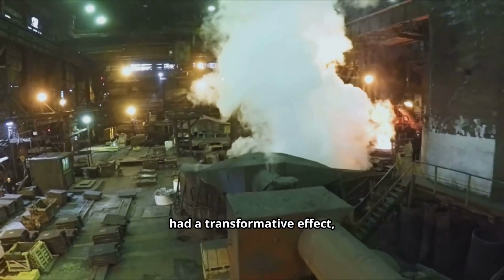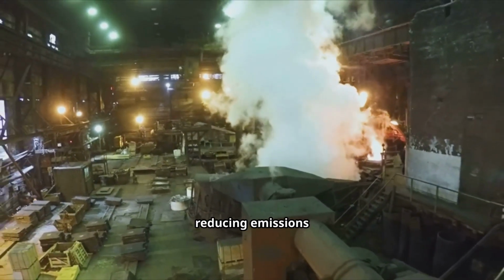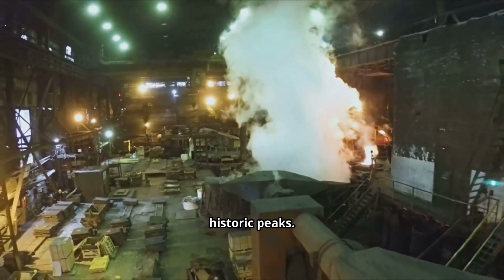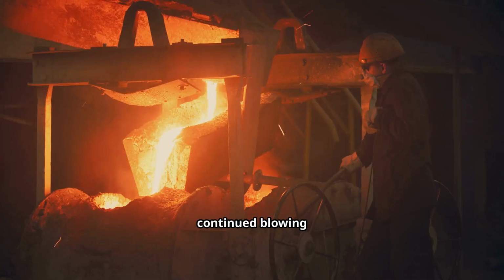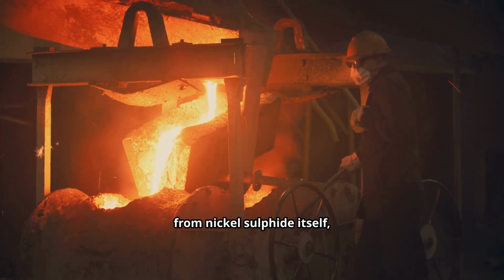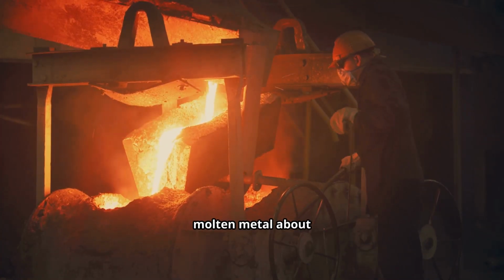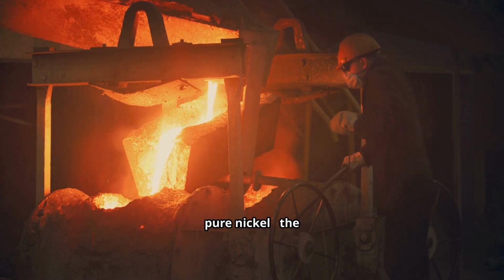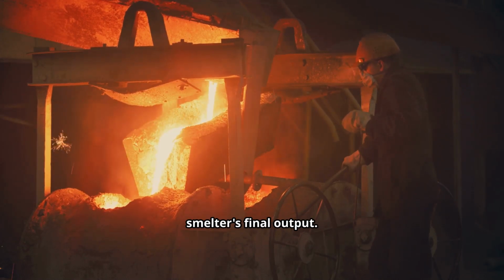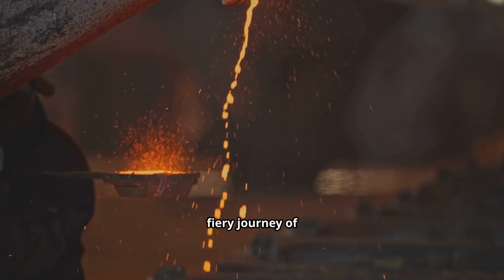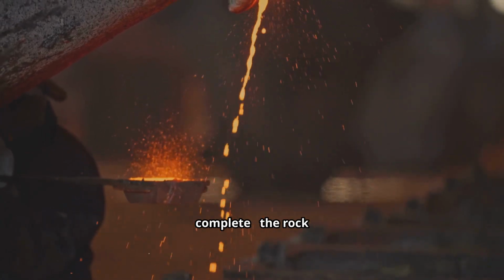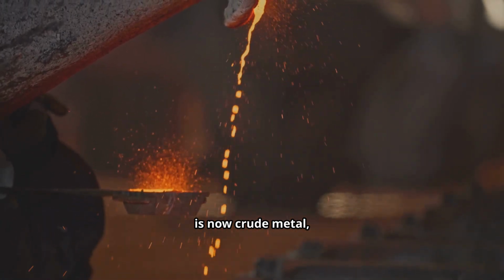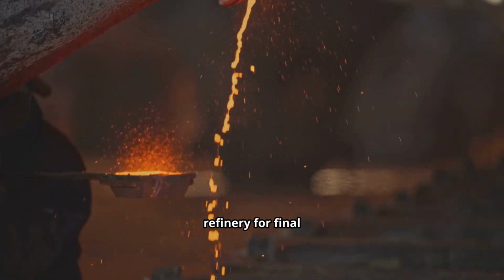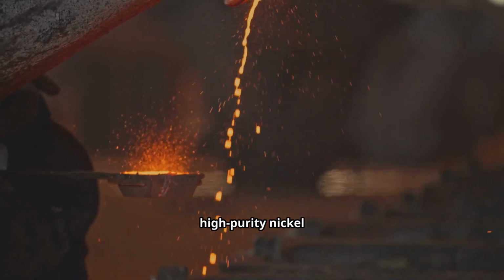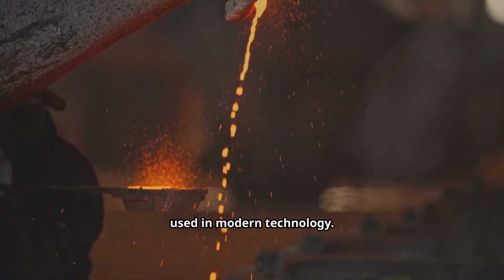This technology has had a transformative effect, reducing emissions by over 90% from historic peaks. Finally, continued blowing drives off sulfur from nickel sulfide itself, leaving behind molten metal about 95% pure nickel, the smelter's final output. The long, fiery journey of pyrometallurgy is complete. The rock is now crude metal, bound for a refinery for final purification into high-purity nickel used in modern technology.